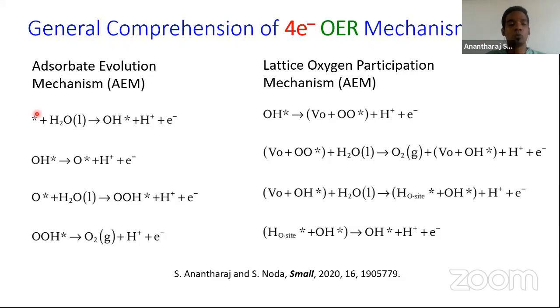lattice. So few people believe that the lattice oxygen does not participate in the oxygen evolution reaction, and few people believe that the lattice oxygen does participate in the oxygen evolution reaction. And there is a huge controversial discussion going on in this area, and we don't want to divert our attention here. Just keep it in mind that an electrocatalyst can perform the oxygen evolution reaction either via adsorbate evolution mechanism or by lattice oxygen participation mechanism. I'm sorry, I put the wrong abbreviation here. It should be LOM. I'm sorry.